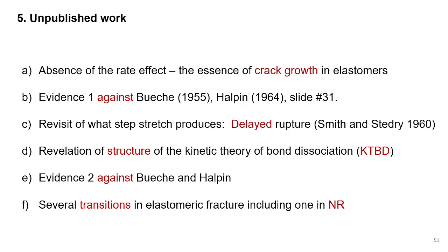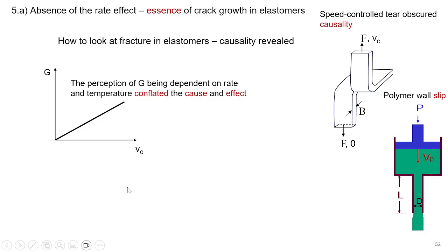I will show you that one of the big confusions is about the rate. I will show you evidence against Bueche and Halpin, twice. One of the confusions in the literature is that they conflated cause and effect. The tearing experiment was misinforming you about the relationship between G and VC, where G is the load and VC is how fast you propagate. This plot should never have been plotted this way. You should always plot VC versus G. In other words, it's the load that's determining the bond tension, and the bond tension determines the lifetime of the bond, and therefore determines the lifetime of the elastomer.